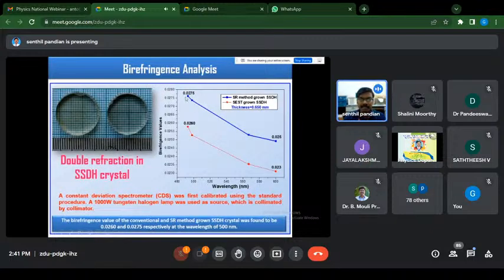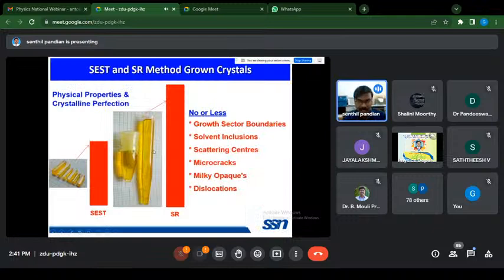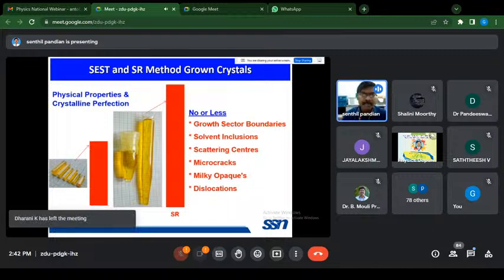And this is the birefringence measurement. See, the birefringence of this SR grown crystal is high because of the higher optical uniformity of this SR grown crystal. So we have grown several crystals, and we have characterized them using HRXRD, UV-Vis-NIR, dielectric permittivity, birefringence, and so on. In the case of crystals grown by the conventional method, because of the large number of grain boundaries, solvent inclusion, entrapment in the crystalline matrix, large number of scattering centers, microcracks, milky opaque regions, and large dislocation density, the physical properties and crystalline perfection of this SEST grown crystal are lower compared to the SR method grown crystal.